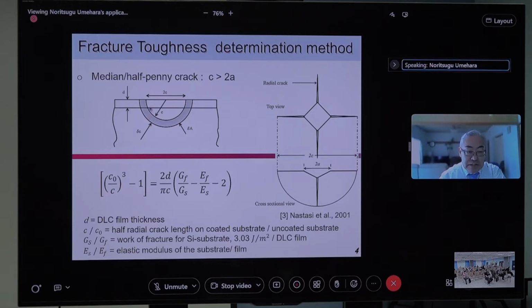So if such a median half-penny crack is expanded like that, some part is in the DLC, some part is in the substrate. After that, they can get such kind of equation. D is the thickness of the DLC, and C is the crack length. G is the work of fracture, E is the Young's modulus. GF is the work of fracture of the film, it's the DLC coating.